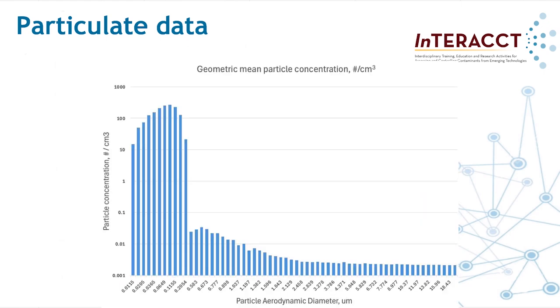You can see here by a different grouping of the data with the nanoparticle data added in, the concentrations of nanoparticles were anywhere from 1 to 4 orders of magnitude higher than the particles in the 1 to 20 micron range. Here again, I had to use a log scale on the y-axis to make the concentrations of larger particles show up on the graph at all. What this means is that this process does emit nanoparticles during all tasks.